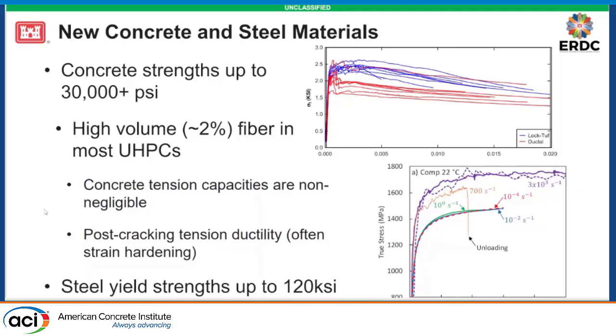The other aspect that I want to point out here is that in this direct tension test, we're seeing strains of 0.02, and this is on a test specimen, I believe, that's about 18 inches long. So it's really an aggregated crack opening more than it is a true strain, because it's not fully distributed. But nevertheless, you're seeing a post-cracking behavior that is very ductile. And I believe there's a large potential benefit to using that kind of ductility in blast designs.